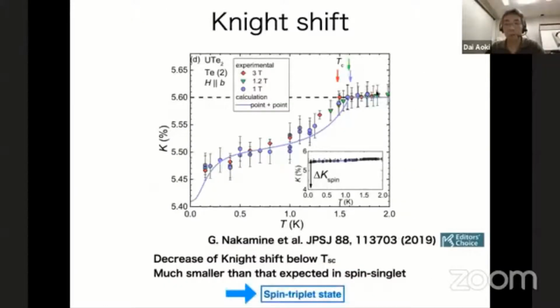Okay, so now I want to show you the results of NMR data. This was measured by Professor Ishida's group at Kyoto University. The Knight shift shows a small decrease below Tc, but it doesn't go to 0. You can see the scale here. Compared to the spin susceptibility, the decrease is quite small. This is much smaller than expected in the case of a spin singlet. So it's a strong indication for the spin triplet state.